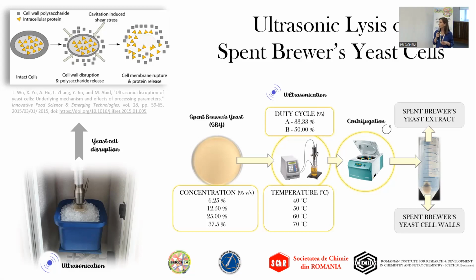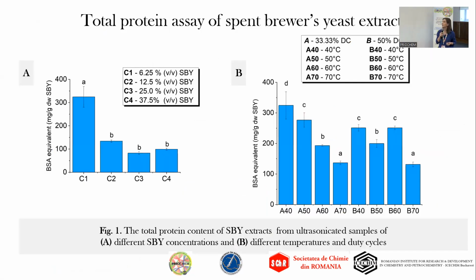In each set, the processing temperature ranged between 40 and 70 degrees. Each sample was finally centrifuged to obtain the yeast derivatives, specifically the yeast extracts and the yeast cell walls. We primarily evaluated lysis efficiency by assessing the protein content of the yeast extracts through the Biuret method. Why? Because a high release of intracellular proteins means an efficient lysis.